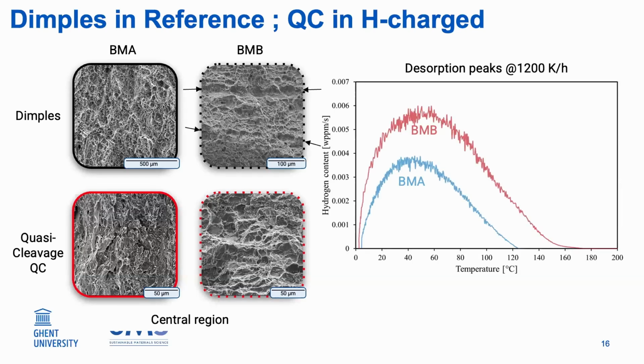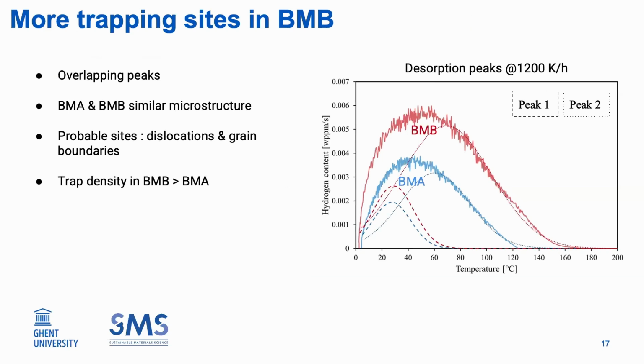A further look into the desorption data shows that a higher desorption peak is present for BMB as compared to BMA, and this accounts for its high hydrogen uptake. Going deeper into the desorption data, fitting it, and then deconvoluting it into sub-peaks, we see that both of these materials have similar overlapping peaks because of their similar microstructure. Moreover, these peaks are only up to 200 degrees Celsius, which is where the reversible traps are present. So we assume that the main players for taking up hydrogen in these materials are grain boundaries and dislocations.